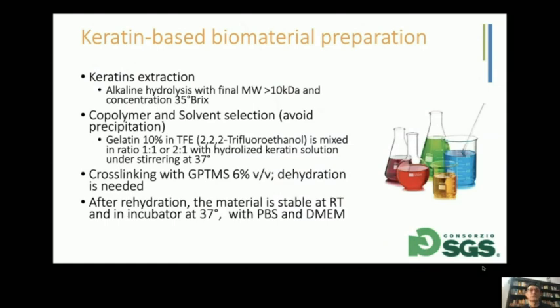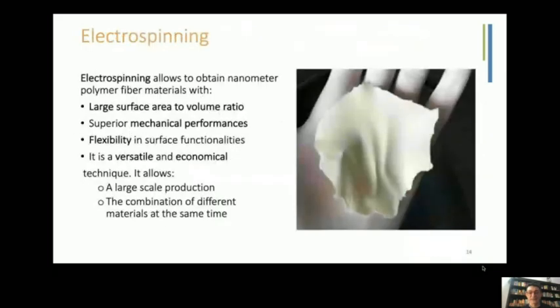With a company close to Pisa, we optimized an extraction process based on alkaline hydrolysis, where we were able to produce keratin with a molecular weight higher than 10 kilodalton. We mixed this keratin with a gelatin solution and cross-linked it with glycidoxypropyltrimethoxysilane (GPTMS), a chemical cross-linker that, after the evaporation of the solvent present in the solution, is able to cross-link the keratin and gelatin. Then the scaffold can be rehydrated in cell culture media, and we obtain a soft scaffold.